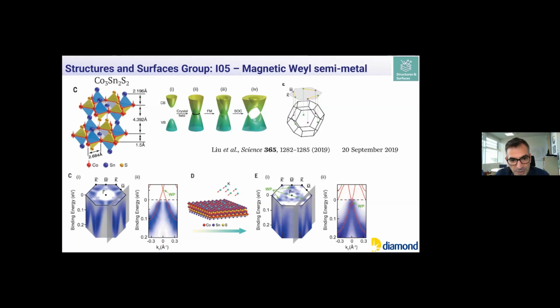And these are systems that have very high mobilities and which can really transform the way we use electronics in the future. So this system was studied using ARPES. This is in the structure and surfaces group. And in this particular study, you can see in principle, with no chemical doping, this Weyl point is not observable. It's well above the Fermi level.